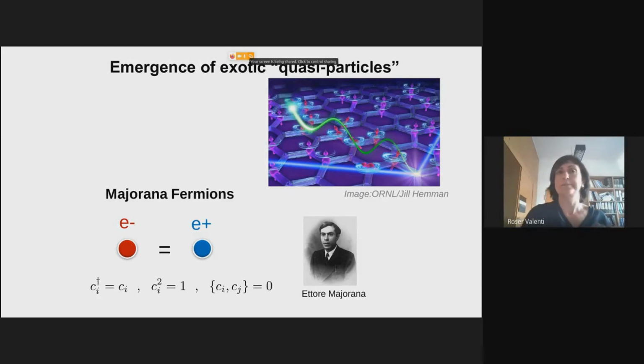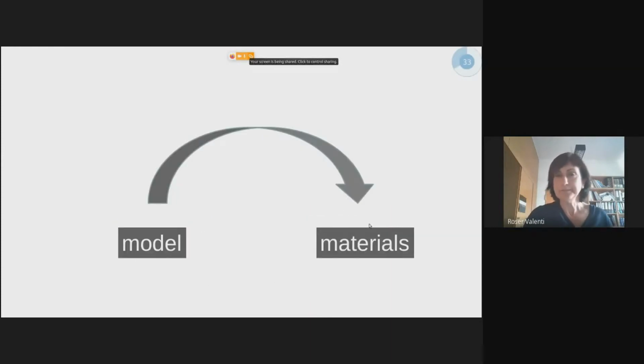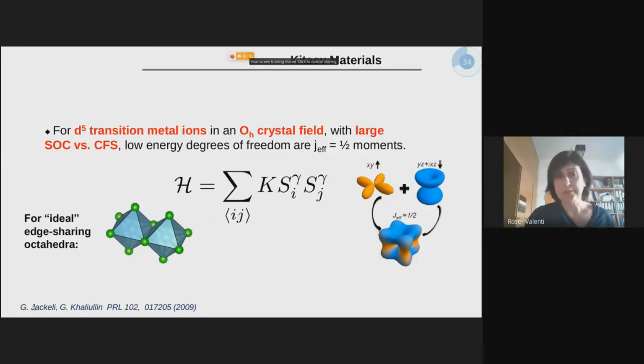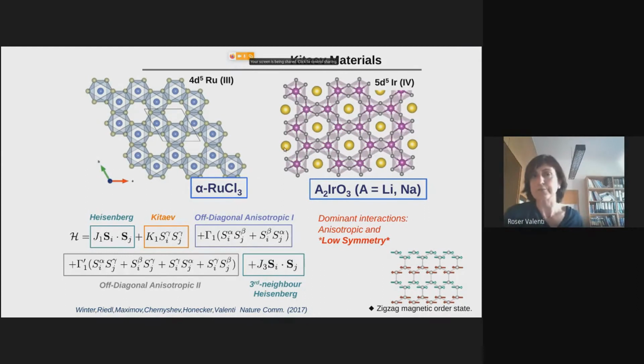Now, the question is, it's a beautiful physics, but can we find a realization of this type of model in a material? And in fact, George Jackeli and Giniyat Khaliullin proposed that this could be realized in materials if one considers materials with a strong spin-orbit coupling and some other conditions, like having d5 transition metal ions forming an octahedral environment and forming edge sharing. So there is a recipe to build up this model in a material. And in fact, there are materials that follow this recipe, like ruthenium trichloride and these iridate materials.